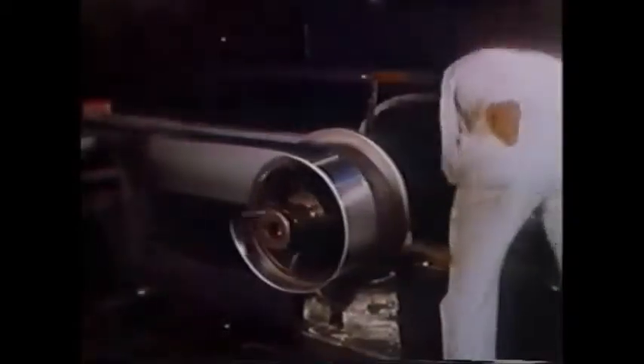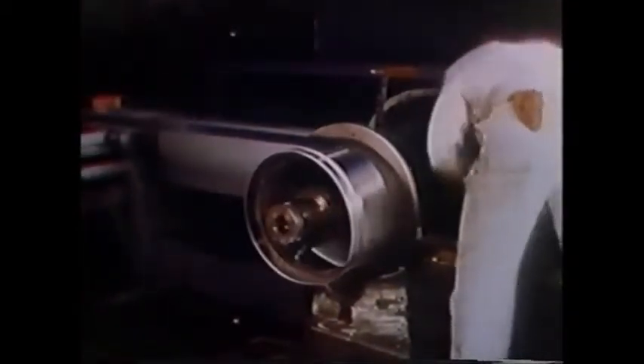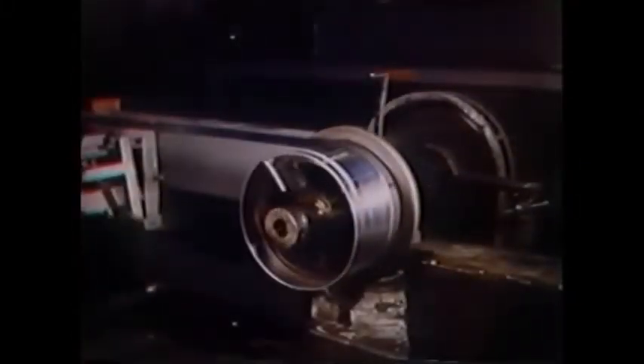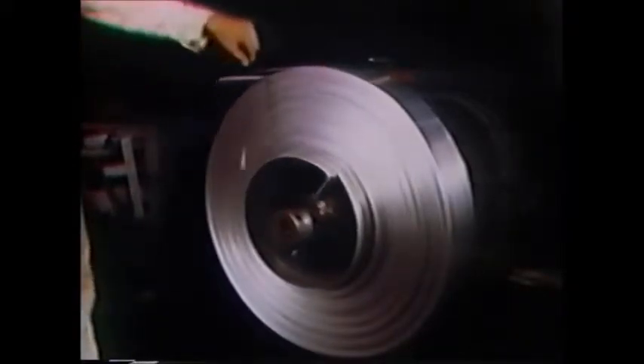The second rolling operation is the gauging operation. In this case, the strip is rolled to 1/8 of an inch in thickness and is coiled in 700-pound coils, as is being done here, or is blanked into aluminum slugs or discs for the subsequent can forming operation. This is a finished lid strip coil. The gauge is checked and the strip is carried over to the blanking press.